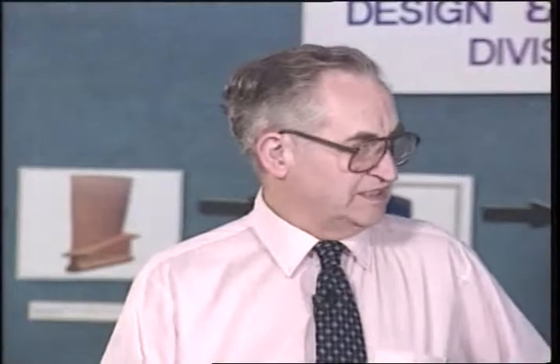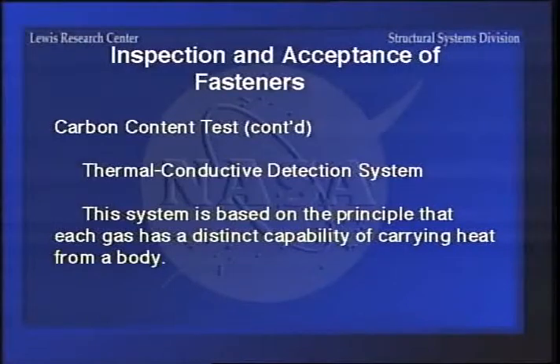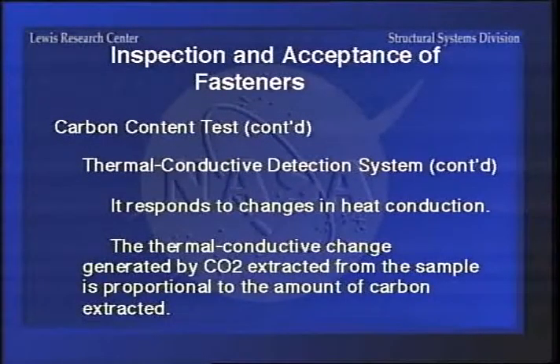On the thermal conductive detection system, it's based on the principle that each gas has a distinct capability of carrying heat from the body. So you can take the carbon dioxide and determine the thermal conductive change generated by it and come up with the amount of carbon that was extracted. In any sense, you can determine the total amount of carbon that was in the sample and get an accurate reading.